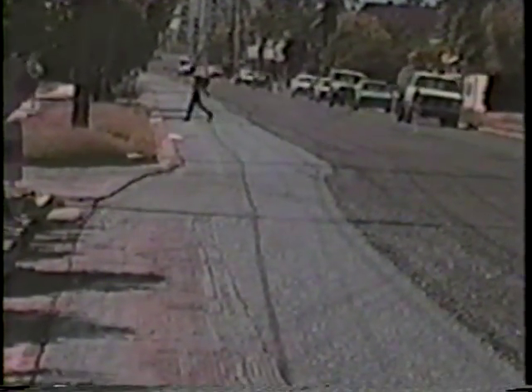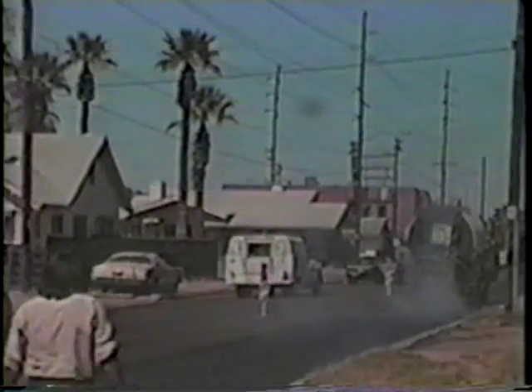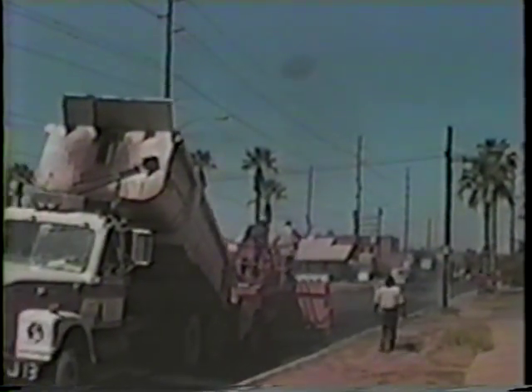It provides a means of restoring rideability and smoothness to distressed concrete pavements as an alternative to expensive grinding, cracking, and seating or thick overlay sections. The stress-absorbing characteristics of the sandwiched asphalt rubber interlayer retards reflection of cracks through the system. It's an effective means of rehabilitating concrete pavements at less than half the cost of grinding.